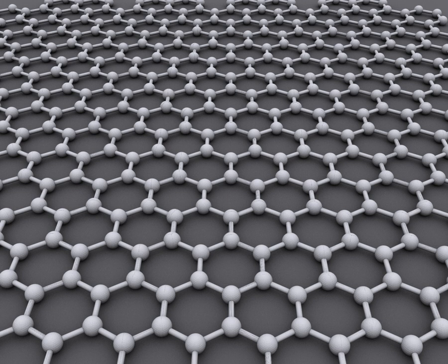Ripples have been observed in suspended layers of graphene. It has been proposed that the ripples are caused by thermal fluctuations in the material. As a consequence of these dynamical deformations, it is debatable whether graphene is truly a 2D structure. In 2014 it was shown that these ripples, if amplified through the introduction of vacancy defects, can impart a negative Poisson's ratio into graphene, resulting in the thinnest auxetic material known.